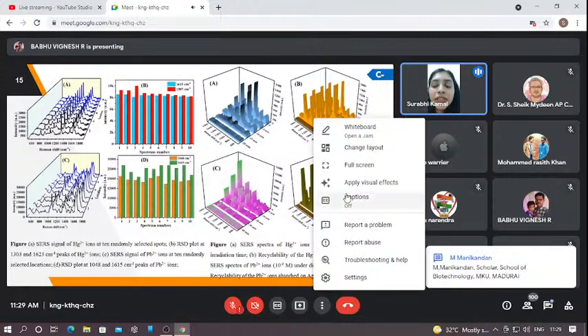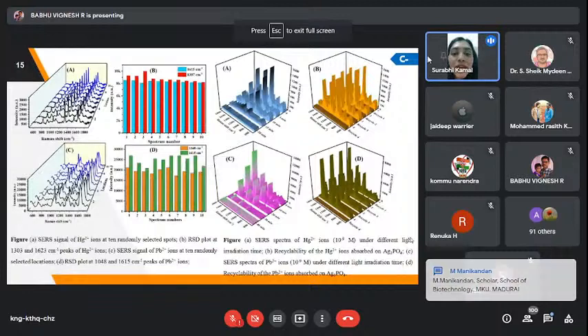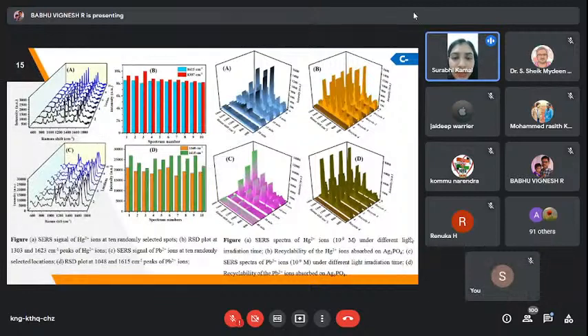I have taken this spectroscopy at different concentrations, and now I have done it with real samples. I have tried spiking with tap water, and in this plot I have plotted the tap water addition, where I have spiked some tap water into it, and done it for reproducibility. The peaks are reformed again in a particular area. So in the first figure, we talk about the reproducibility, and the next figure talks about the degradation. We have used the same substrate material platform, degraded the material, and then used it again. I have done four cycles for this degradation method, and it can be reused as well.